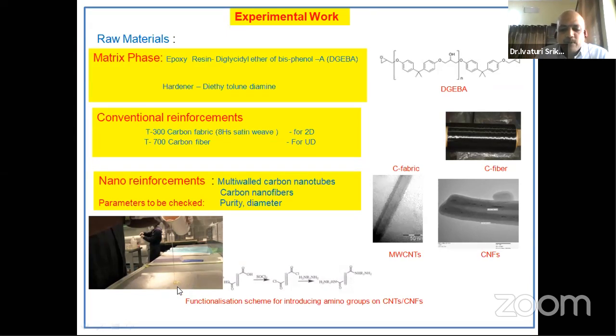We also realized UD composites, meaning filament wound composites. I have shown you in one of the slides the filament winding process. So filament wound composites are called UD composites. We have experimented with both UD and 2D composites. These are some of the SEM, TEM images of our multi-wall carbon nanotubes that we have used. We have also used carbon nanofibers. Carbon nanofiber is a kind of crude form of nanotube with a thick shell on the surface, whereas here you get a very thin shell, and as compared to the hollow core of the nanomaterial. These are the regular carbon fiber images that we have used.